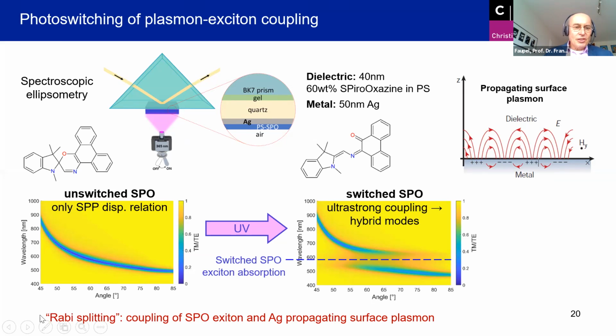So physicists call this Rabi splitting. And this means that the resonance frequency of the individual oscillators splits into separate resonance frequencies. And our idea is to use this, as I said, for all optical switching by using such photoswitchable chromophores. And the chromophores which we used here, SPO, they can be switched from a state where this ring is closed to an open state. And this can be done reversibly with UV light, and back switching occurs with visible light.